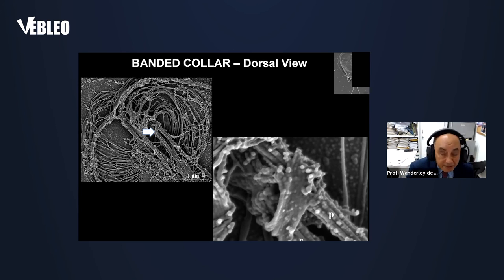One advantage of helium ion microscopy is that there is no electric discharge. So I don't need to coat, I don't need to put anything on the sample that I am going to observe. Therefore, this significantly increases the resolution of the microscope. And now, instead of 0.8 nanometer, we can achieve 0.2 to 0.3 nanometers. Therefore, some structures that I don't see using the scanning electron microscope, I can see using the helium ion microscope.